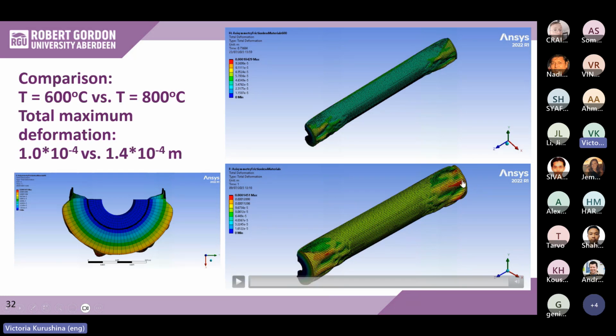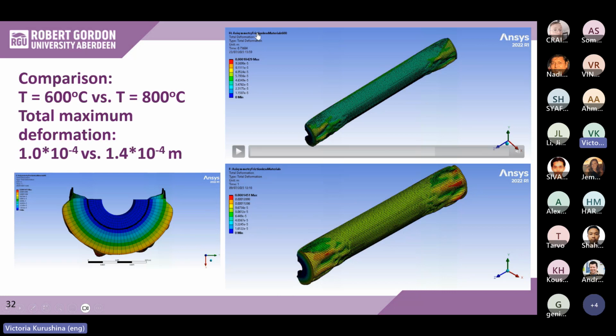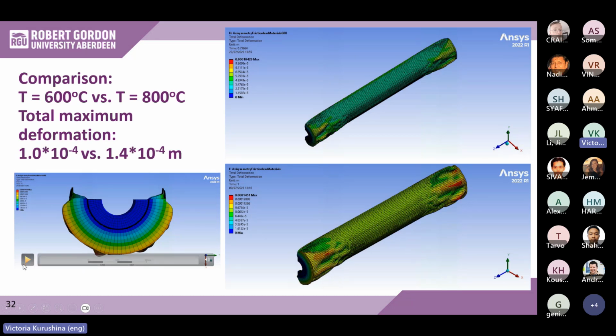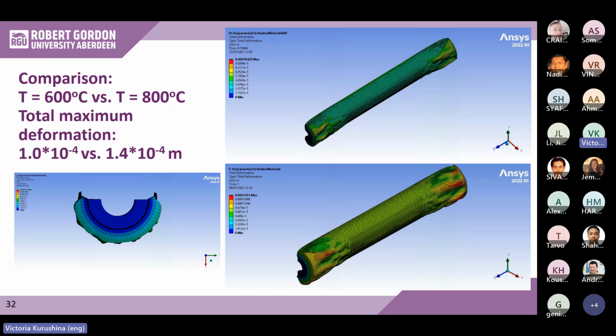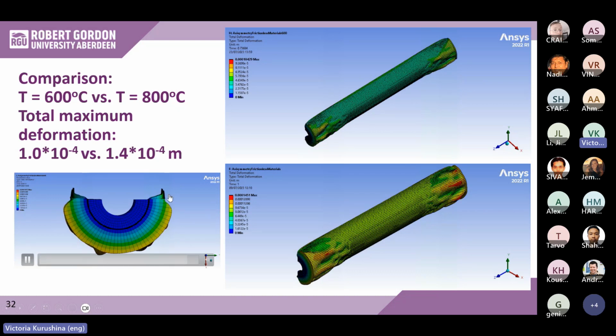Respectively, it's located near the fixed connections for 800 degrees, and for 600 degrees it's also located in this area, but the value of the maximum deformation is significantly different. If we take a view from the fixed connection surface, you will see how this expansion grows. And in this specific video, we allow the outer functional layers to expand, so you can see this difference in expansion.